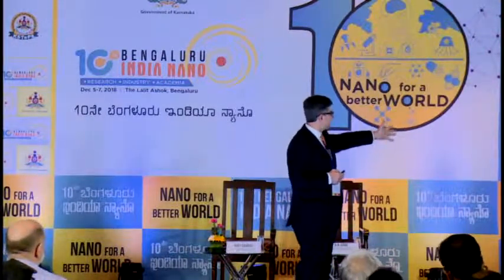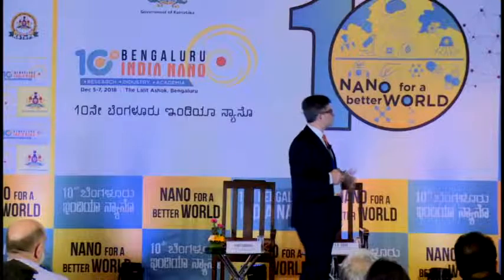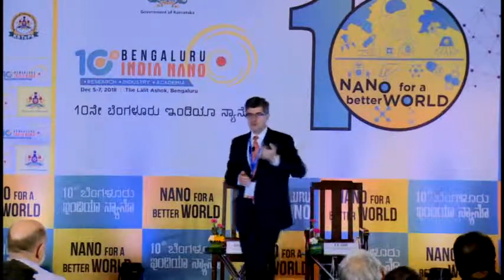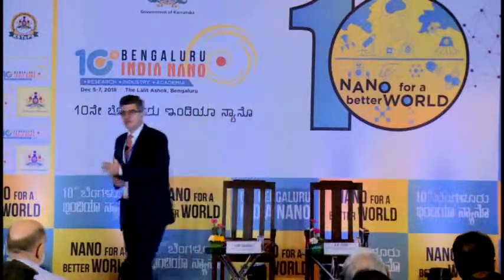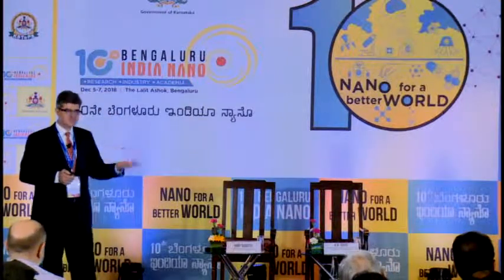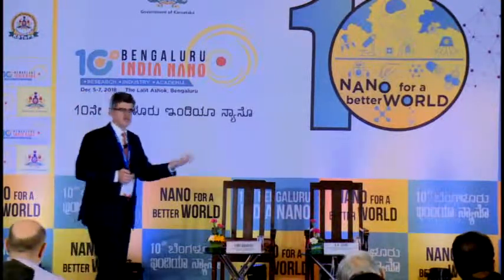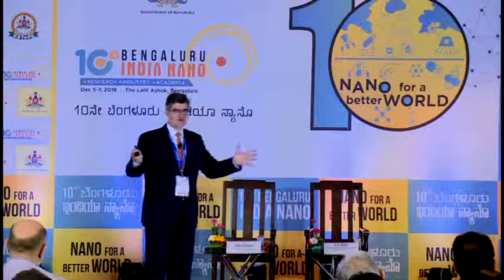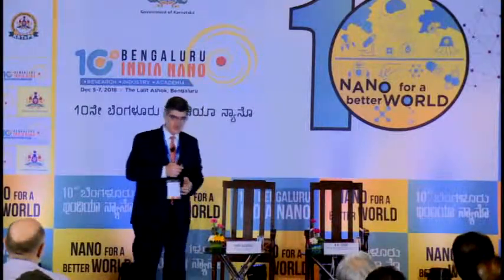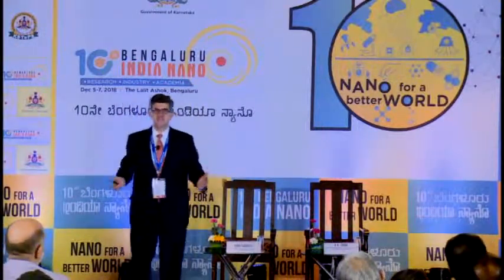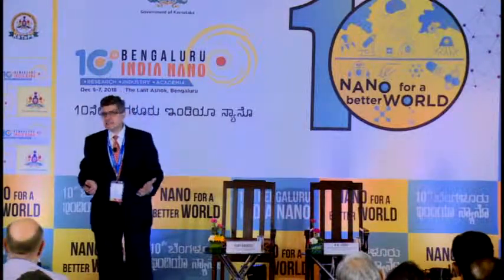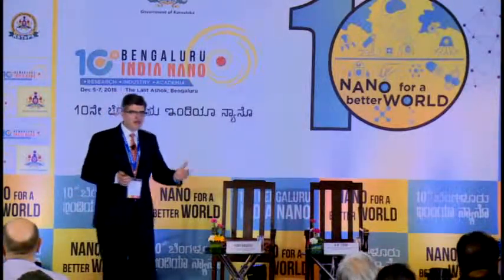You see, it's an undergraduate student who did synthesis of 40 grams of Mo2TiC2, and we can delaminate it all into single-layer particles with few nanometers, or few micrometers to about 20 micrometers lateral size here. And this is very, very important. So it is an intrinsically scalable nanotechnology.